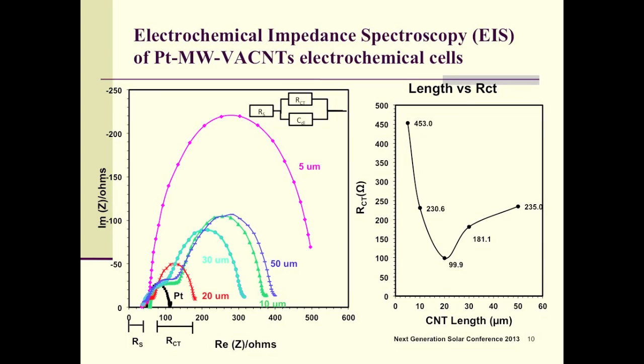And these are the Nyquist plots of the electrochemical cell, in which one electrode is platinum, the other is the multi-wall carbon nanotubes electrode. In the equivalent circuit, the parallel combination of RCT and the double layer capacitance gives us this semicircle, and the diameter of the semicircle gives us the RCT. We observed that with increasing length up to 20 micrometer, the diameter becomes smaller and smaller, and then after 20 micron it is again increased. So it shows that the 20 micron carbon nanotube electrochemical cell has given us lower charge transfer resistance.